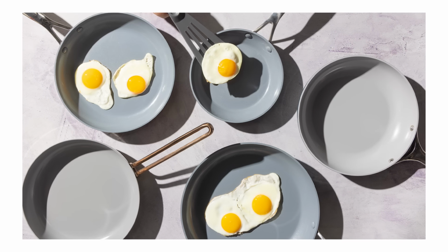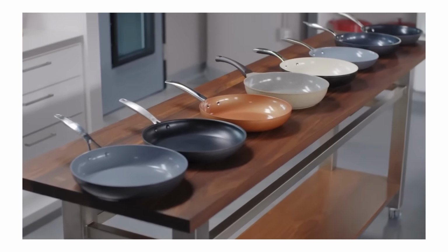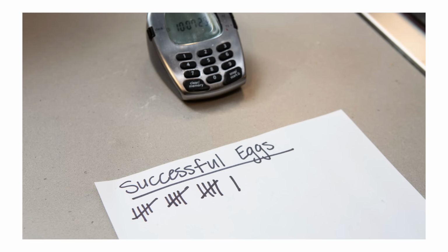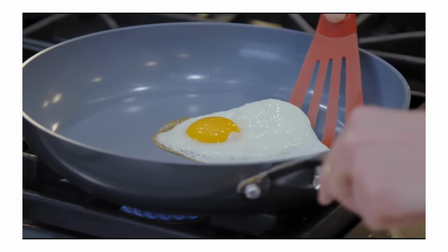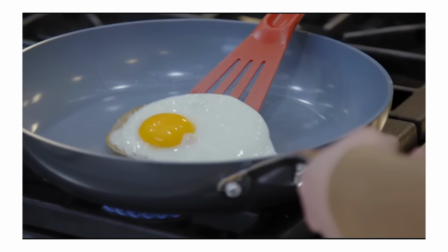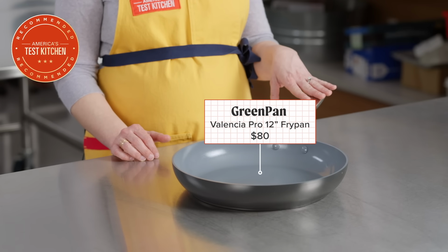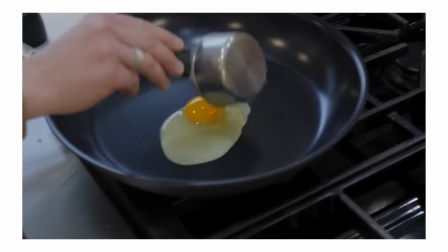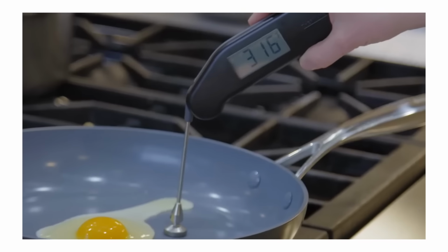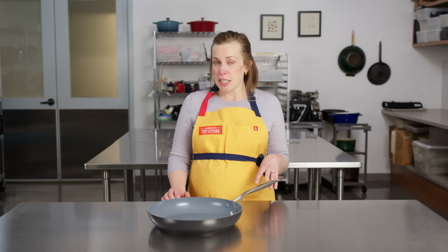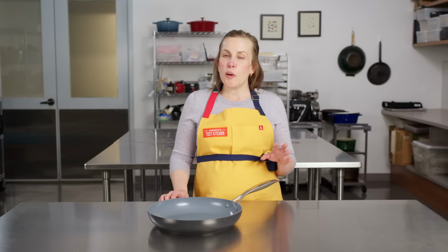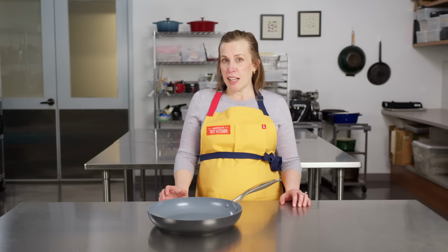We recently tested 14 of these ceramic skillets using the same criteria as our testing for traditional nonstick skillets. Some were really bad, but the good ones were great. Maybe not quite as good as our Teflon winners, but only by a little. This is our winner from Green Pan. It aced most of our tests, including the standard 50-egg test, releasing each egg beautifully. Other ceramic skillets started sticking around 7 eggs, which is abysmal. Only 3 ceramic skillets passed that test. The whole point of these pans is their non-stickability, so failing the egg test is a non-starter.